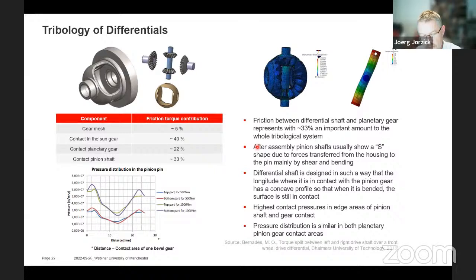So far we talked a lot about combustion engines, but right now, of course, everybody's talking e-mobility. So also parts from electric vehicles are coated, and I already mentioned here the differential shaft. For this application, typically the majority of the parts got a different surface treatment, electroless nickel, and due to the increasing torques and higher loads, this is somehow limited, so that for electromobility especially, more and more PVD coatings are used. And this is again a DLC coating or a titanium nitride. And you see also here in this simulation that this shaft is highly bent, so it's a very dynamic component, so the coating also needs to be able to perform under these kinds of harsh conditions.